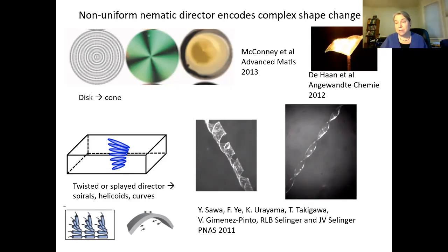Well, the same kind of thing can be done here, and we can have a liquid crystal film that has a twist of the nematic director from one side across the very thinnest axis of the film. And then when you heat it, it can form into some kind of helix. And now we are inspired by Italian pasta. What kind of pasta looks like this? What kind of pasta looks like this? So this is more like rotini. This is more of a hollow tube.